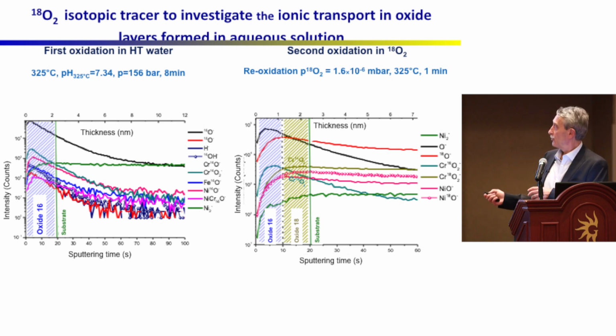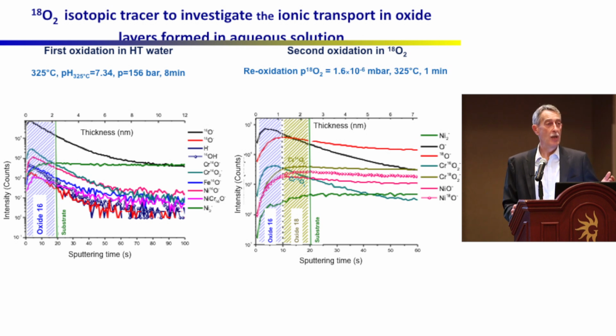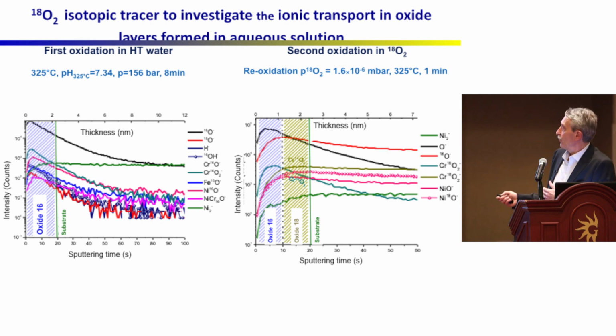I'm not going into the details, but from all of these profiles, we can already come out with a model of the film with an outer layer rich in iron and nickel, and an inner layer rich in chromium oxide and the spinel NiCr2O4. That's not what I want to show now, but this is already a very important result. We can also look at the kinetics, because this is the signal of Ni2- ions. So this is the substrate. When we come on this flat part here, it means we have the interface.